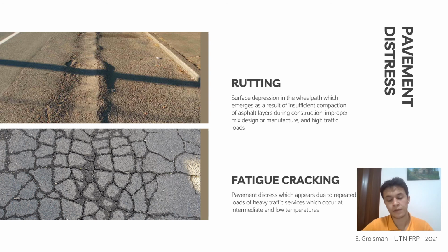But different studies show that the increase in the ductility and the elastic recovery, which is due to the use of crumb rubber in the asphaltic mixture, provides us an opportunity to reduce the plastic deformation which gives rise to fatigue cracking. Why? Because by having a higher elastic recovery and ductility, the asphalt can deform but always comes back to its original shape when the compression load of the car tires is removed.